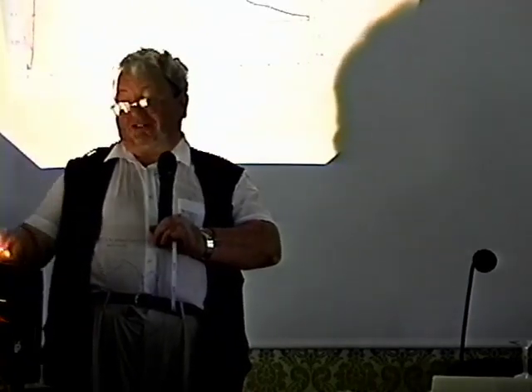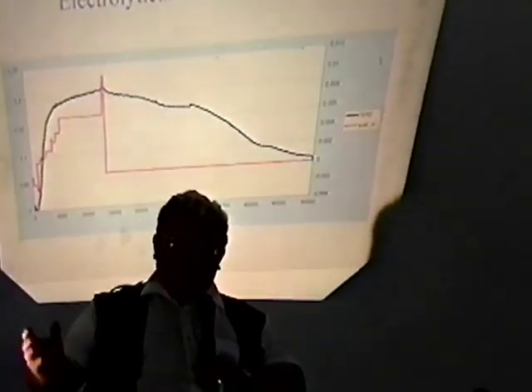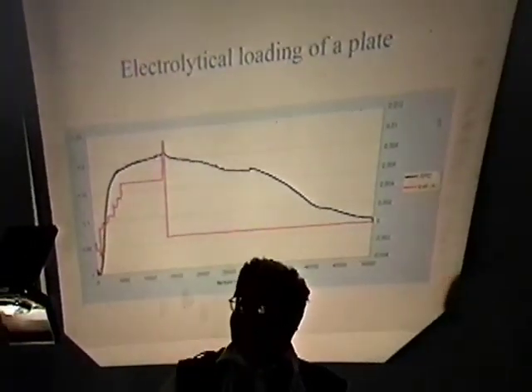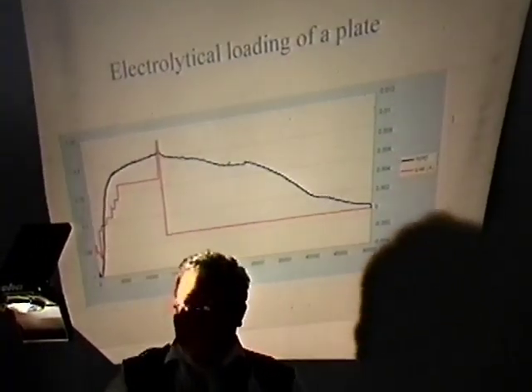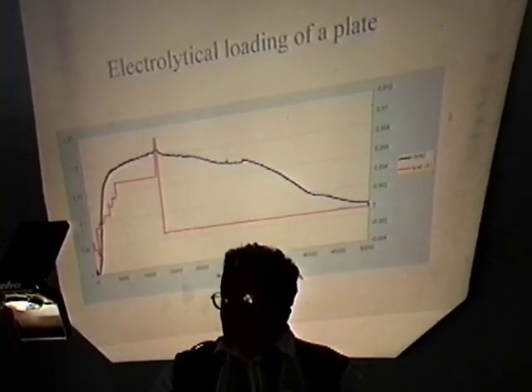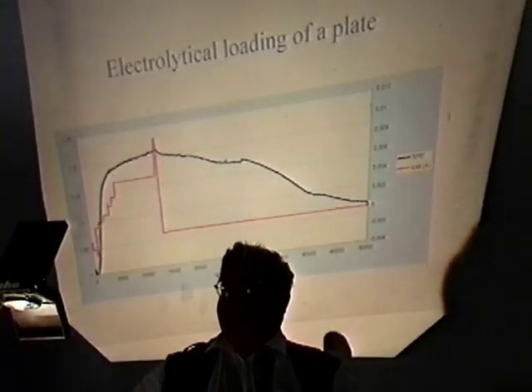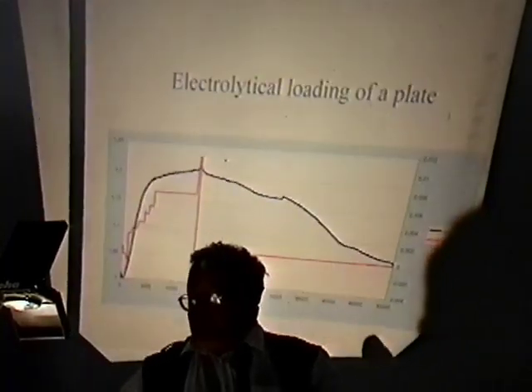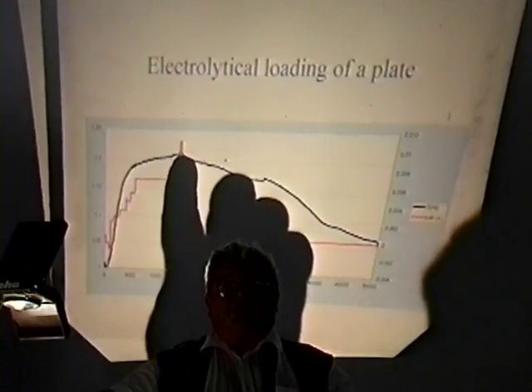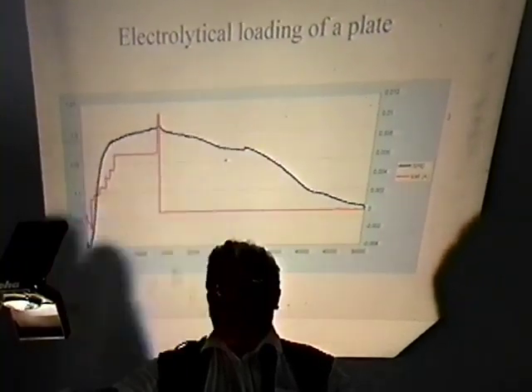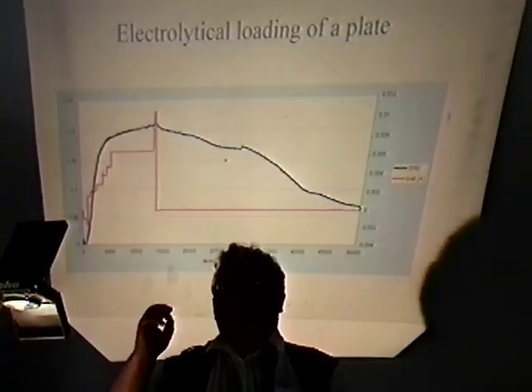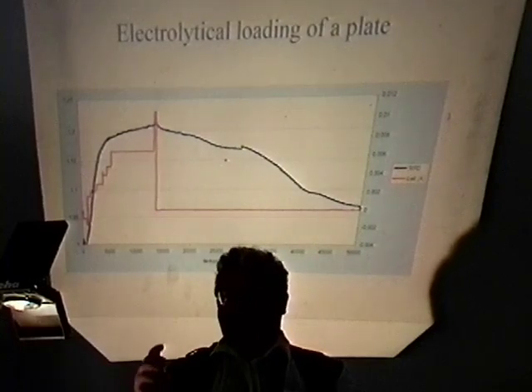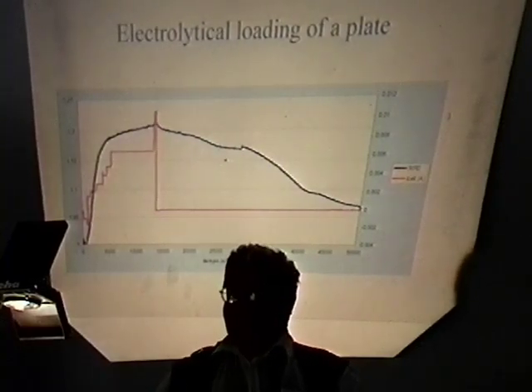That the system has been loaded only to the beta phase, because we are on the left side of the Baranowski curve. I will show you the Baranowski curve now. Because when we remove the current, the system discharges. The peak of R over R naught is much lower than in the original Baranowski curve, because of a phenomenon I will describe to you in a while.